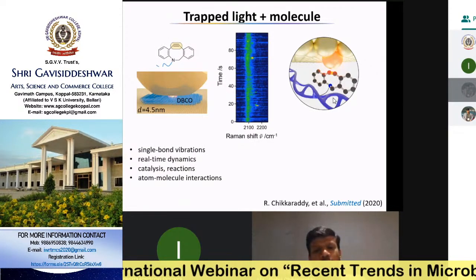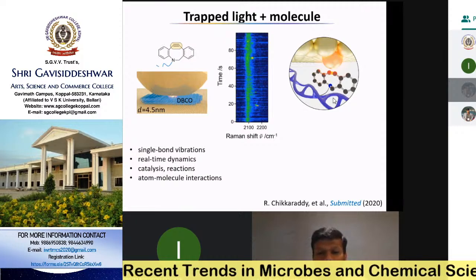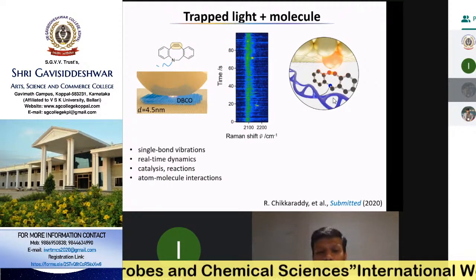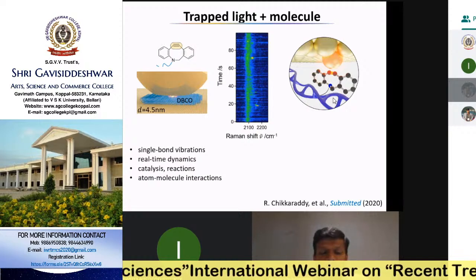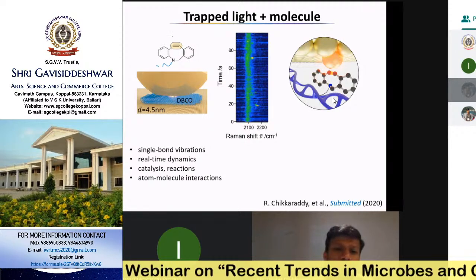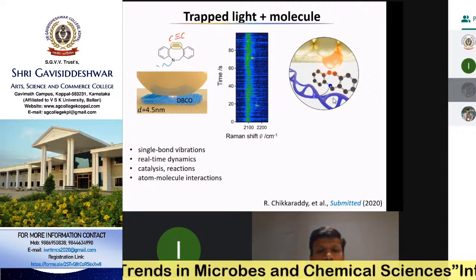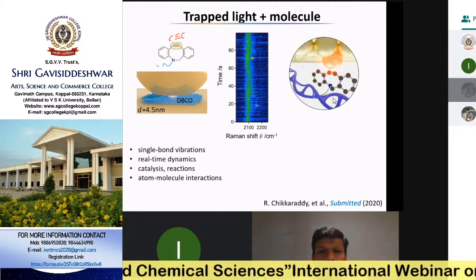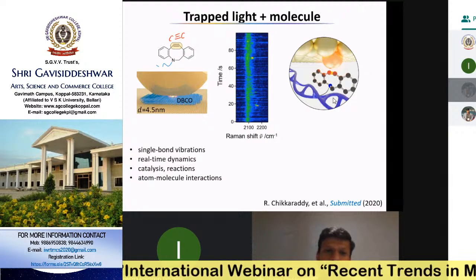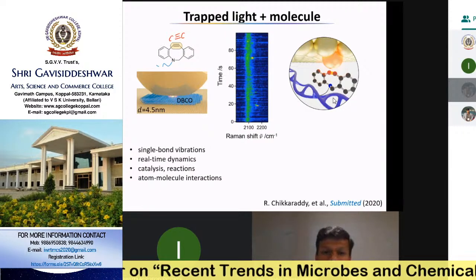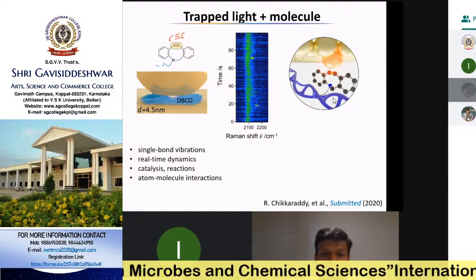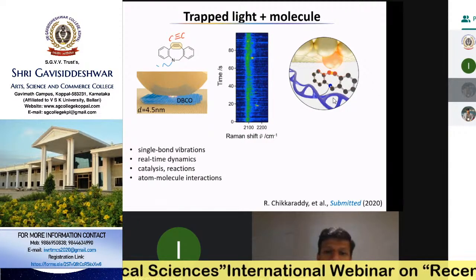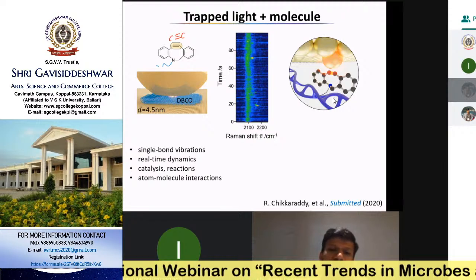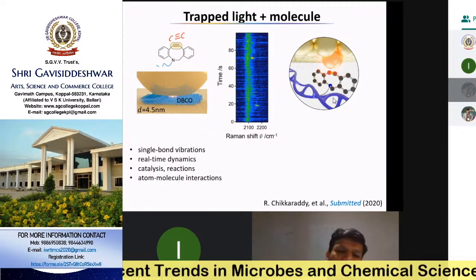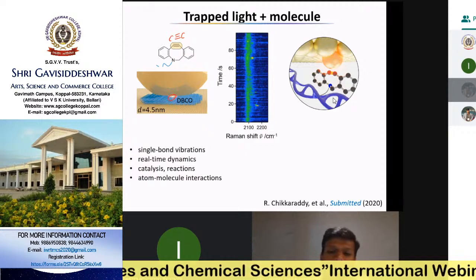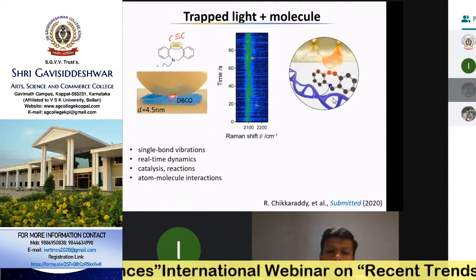From a chemistry viewpoint, as I said, you can do Raman spectroscopy. You can look at the vibration of the molecule. In this particular case, you take a molecule which has a very unique bond vibration. We see a C triple bond C. Most chemistry people would understand that C triple bond C has a strength of vibration much larger than C double bond C or even C single bond C. So C triple bond C, which is an sp hybridized bond, has a very high energy, and we can watch the vibration of this one single bond sitting in this trapped light, which gives a unique fingerprint vibrational spectrum.